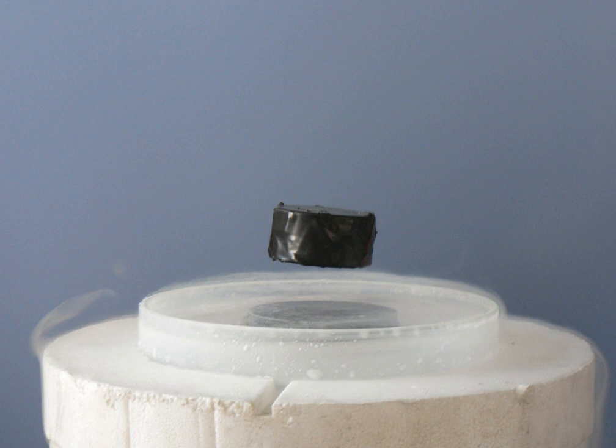In a class of superconductors known as type 2 superconductors, including all known high-temperature superconductors, an extremely low but nonzero resistivity appears at temperatures not too far below the nominal superconducting transition when an electric current is applied in conjunction with a strong magnetic field, which may be caused by the electric current. This is due to the motion of magnetic vortices in the electronic superfluid, which dissipates some of the energy carried by the current. If the current is sufficiently small, the vortices are stationary, and the resistivity vanishes. The resistance due to this effect is tiny compared with that of non-superconducting materials, but must be taken into account in sensitive experiments. However, as the temperature decreases far enough below the nominal superconducting transition, these vortices can become frozen into a disordered but stationary phase known as a vortex glass. Below this vortex glass transition temperature, the resistance of the material becomes truly zero.